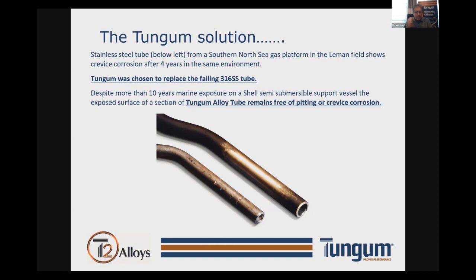The important part for the user to understand is that that particular film, the film that you see here in brown, is an oxide layer of Tungum that has formed. Over time, that oxide layer forms upon itself and morphs into these various colors. The oxide layer never penetrates into the base material. And that's important to understand, because what that means to the end user is that although the surface is changing colors, the material remains 100% intact. The wall thickness is still there to support the pressures, and therefore there are no issues with respect to leaks.